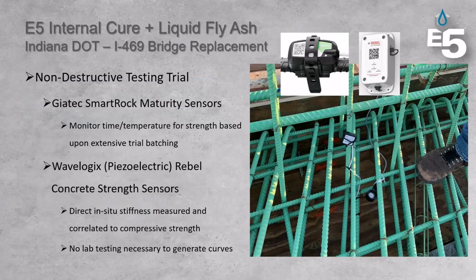Picture of the hardened deck. Some sensors that were used, basically the Giatec SmartRock maturity sensors were used. We're all familiar with those. You do lab testing. You establish a maturity curve for temperature versus strength. And instead of using companion cylinders, which aren't as representative, you monitor some in situ temperature curves or temperatures using Smart Rock maturity sensors, and you identify strength, and then you can hit it without relying on the lab to give you those breaks. Dr.